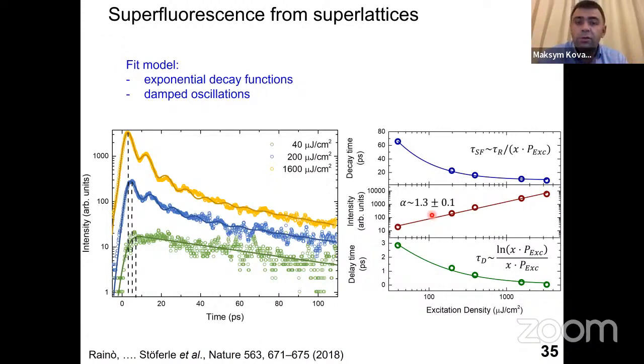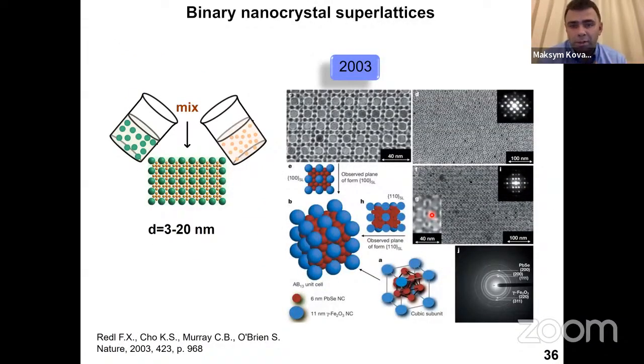So this property is called superfluorescence, and we were very excited to observe that because it's simply the first chemically produced quantum dot system which exhibits this property. So far, it had been observed in very few cases: epitaxial quantum dots of one kind, as well as some atomically doped alkali metal halides, or even some gases such as hydrogen fluoride. But now you have a solid state system where you can potentially tune this property through composition, through size, through nanocrystal assembly, and you can basically engineer this property. It's not that you can just observe it. And so we were extremely motivated to try to engineer this property further.